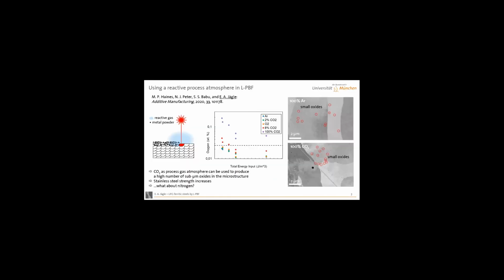In the case of the CO2 study that I mentioned in the very beginning, we did indeed change the oxygen partial pressure. So we had argon plus various different CO2 partial pressures. And we first started, very, very carefully, with argon plus 2000 ppm of oxygen. So that's 0.2% of oxygen. Because we were really afraid, and basically nothing changed. And then we took 2% of CO2, still nothing happened. 8% of CO2, small effect. We started going to oxygen contents higher than the powder oxygen content. And then I said, okay, forget about it. Let's take the bottle with 100% CO2. And that was actually the most interesting one.